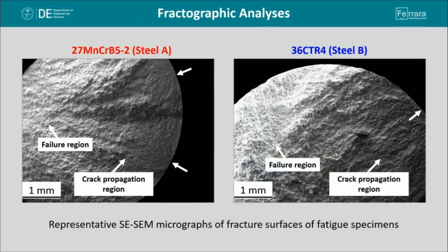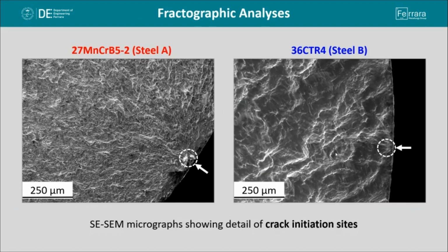In this case, we can see that both specimens exhibited crack initiation sites located at the external surface. So we are dealing with the typical morphologies related to rotating bending fatigue tests. Together with these crack initiation sites, the specimens exhibited a flat crack propagation region and finally a final failure region, which appeared more fibrous. At high magnification, we detected that crack initiation sites were associated with surface and subsurface defects, which eventually promoted the initiation of failure.